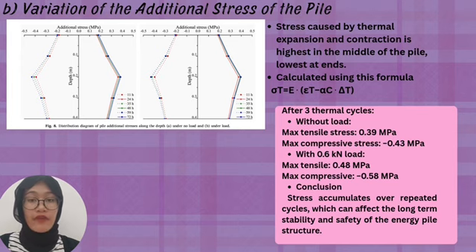Additional stress in the pile. Due to thermal expansion and contraction, the pile experienced internal stress during the thermal cycle. The stress was highest in the middle of the pile and lower at both ends. Under load, the maximum tensile stress reached 0.48 MPa and compressive stress reached negative 0.58 MPa after the third cycle. These values were higher than under no load condition. Also, stress increased with each cycle, indicating residual thermal stress accumulation. This is critical for long-term structural safety.